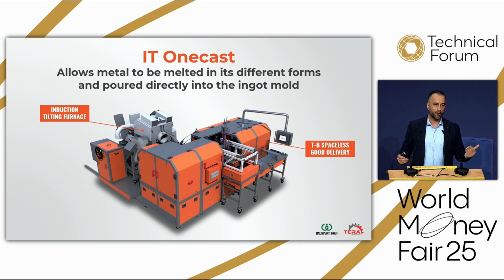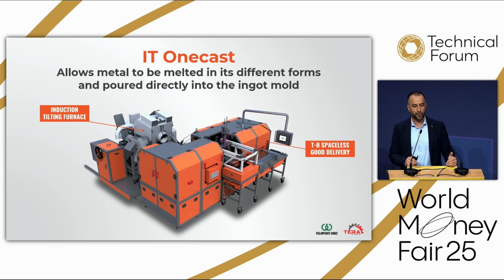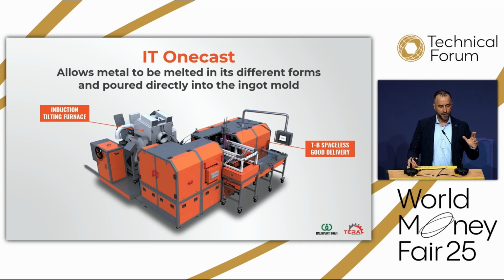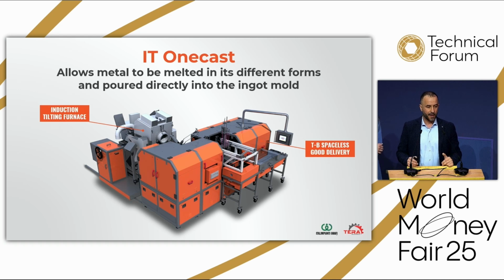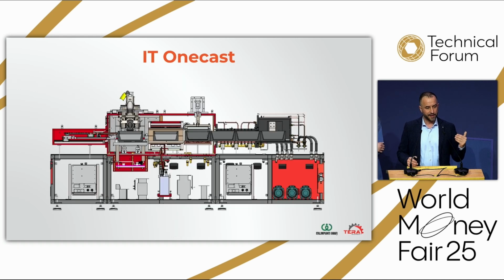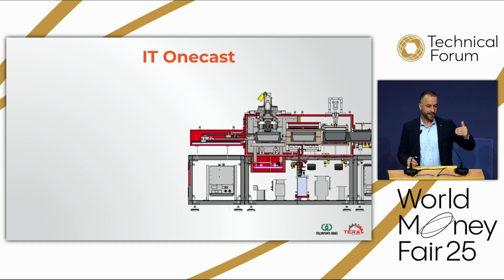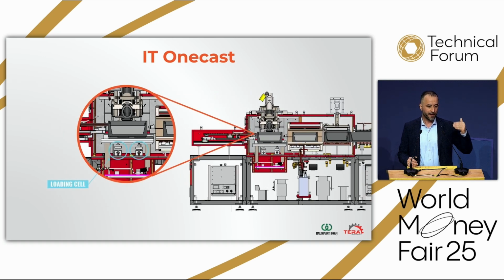Namely, we load the crucible of the tilting furnace with a known amount of crystals, in case of silver, for instance, and we target a weight of 30 kg, the traditional good delivery bar for silver. Once the recipe is loaded and we start the system, automatic pouring of the tilting furnace will occur and the metal will flow into the mold. The mold itself is placed over a load cell.